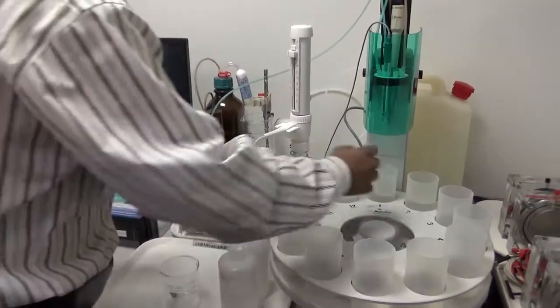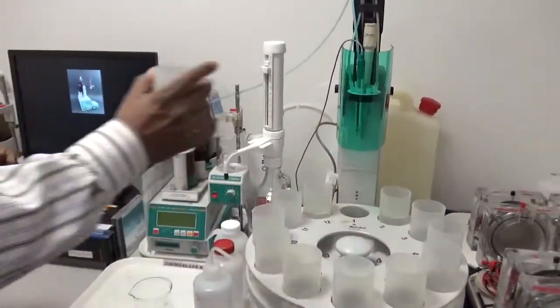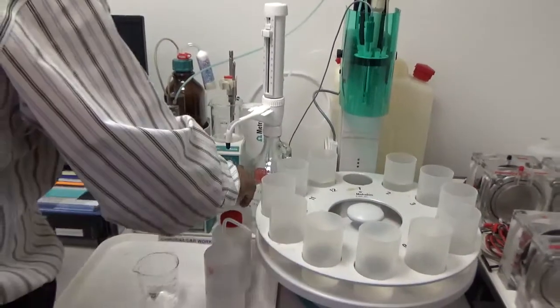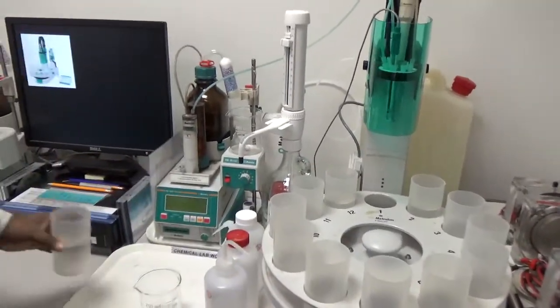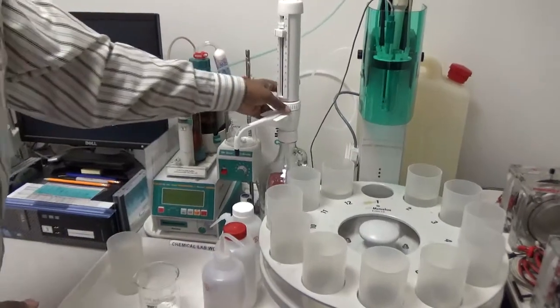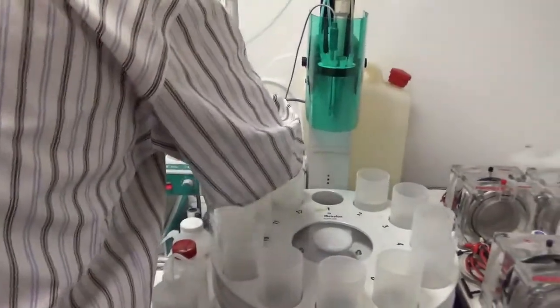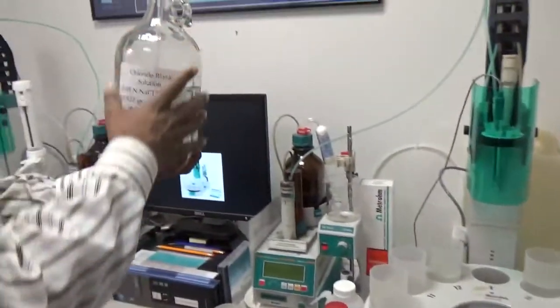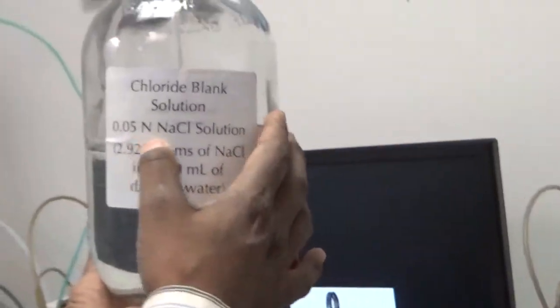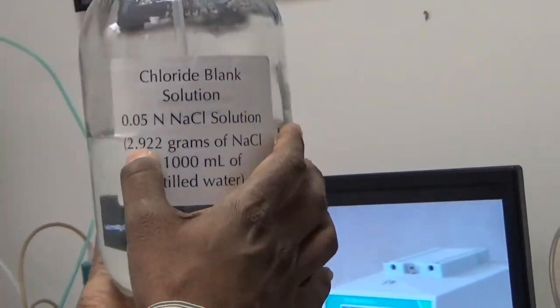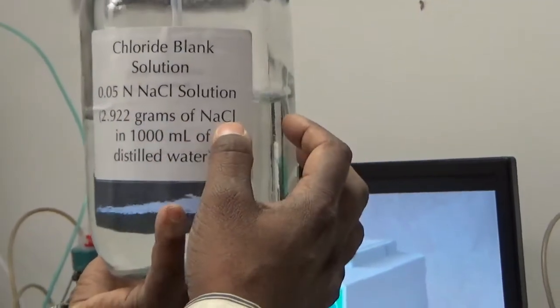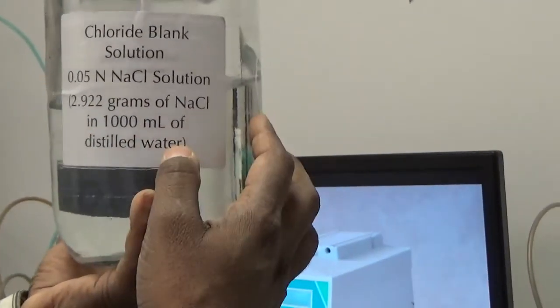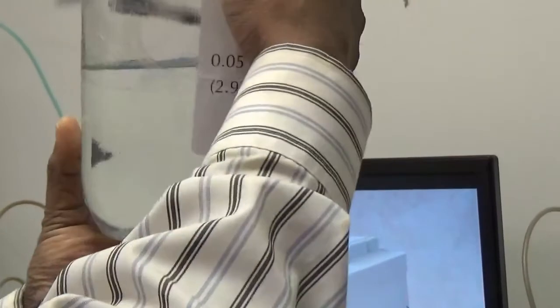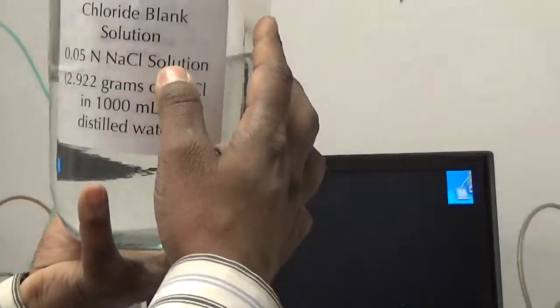To use the blank solution, we take distilled water, and in the distilled water we add 5 milliliters of sodium chloride solution, which is a blank solution. The sodium chloride solution we prepare is a 0.05 normal sodium chloride solution, prepared by adding 2.922 grams of sodium chloride in 1000 milliliters of distilled water. That's how we prepared the standard solution of sodium chloride.